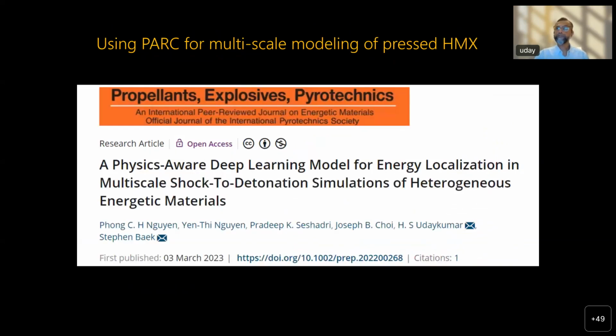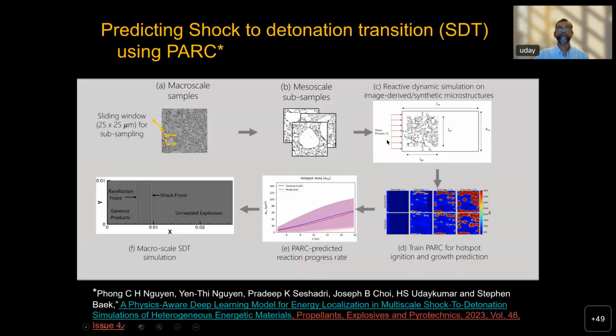Now we've used this PARC model to do the full multi-scale analysis. That came out in a paper in PEP just recently, where we can take a macro scale image sample, do the statistical analysis of it, do DNS simulations, train PARC, and then PARC predicts the hotspot growth rate and so on, and we feed that to the macro scale simulation and predict SDT and the criticality envelope.